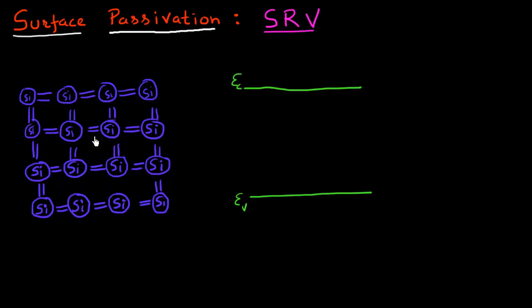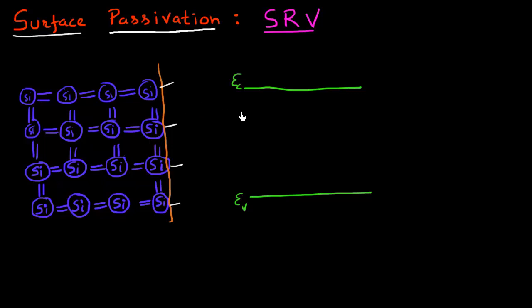This is all fine and true when you have a large lattice or a large number of silicon atoms. But things begin to falter as I move to the surface. When I reach the surface, I see silicon atoms which have not fulfilled all their bonding requirements — all of these silicon atoms have one or more dangling bonds. Ideally they would like another silicon atom to be present on the other side, but since it's not, it breaks the symmetry of this lattice. And it results in the formation of states which appear in this forbidden region, or in this band gap region of my semiconductor. These are typically what is called surface states.